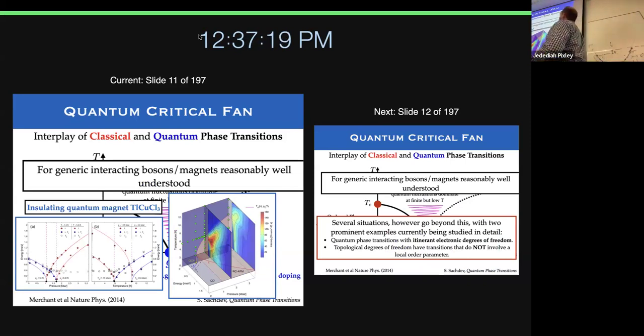TLCuCl3 is a beautiful system. It can be tuned with pressure or magnetic field. Here I'm showing pressure tuning, and they can realize these classical and quantum phase transitions, and this is neutron scattering. They can see the two different universal critical exponents of the two different transitions, the finite temperature classical transition and the zero temperature quantum transition.